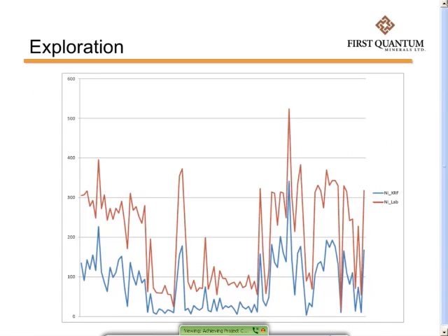This expands on the previous example. Nickel data in red is the lab and the blue is the XRF. The XRF significantly underestimates the true value, but consistently. This allows the identification of relative anomalies, low, medium and high, aiding in targeting and allowing FQM to focus their efforts in particular areas and utilise their time more effectively.